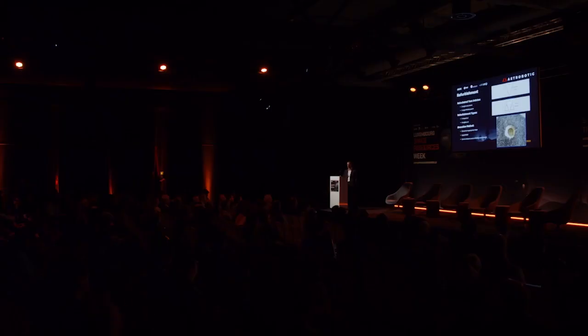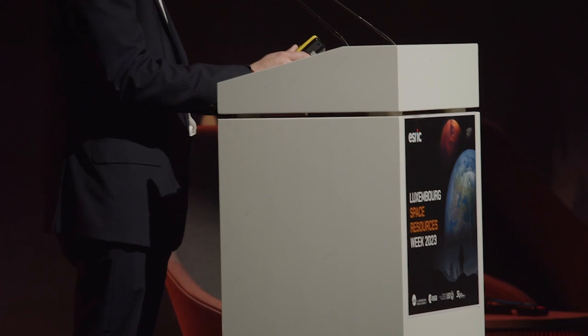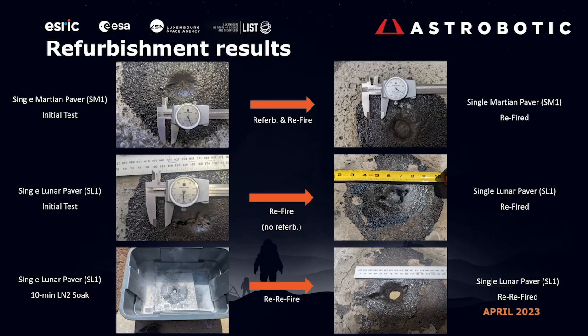What if we can use it to repair the pavers? So we did a little bit of surface prep to ensure good bonding. Some of the samples we didn't undercut, some of them we just did a surface preparation. Then we reapplied the landing pad material and re-cured it in a vacuum or CO2 environment and fired on them again. So the results of the refurbishment were really compelling. The pads performed as well or better than the new pads after they had been repaired.